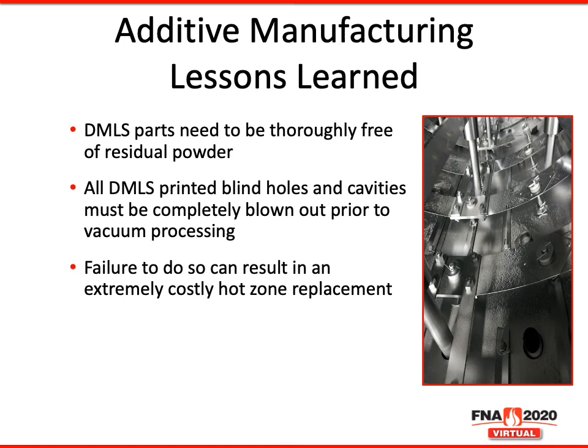So, some other lessons learned. These are some DMLS parts that need to be thoroughly free of residual powder. All the printed blind holes and cavities must be completely blown out prior to vacuum processing. Failure to do this can result in extremely costly hot zone replacement.